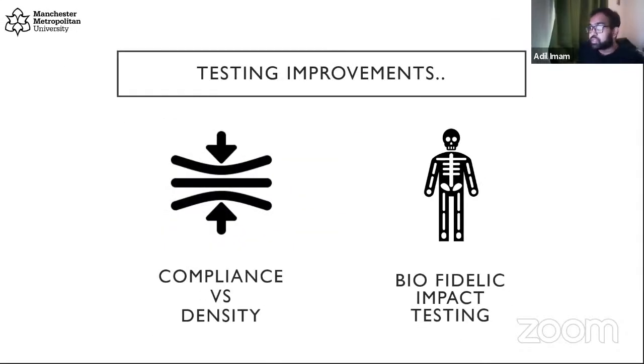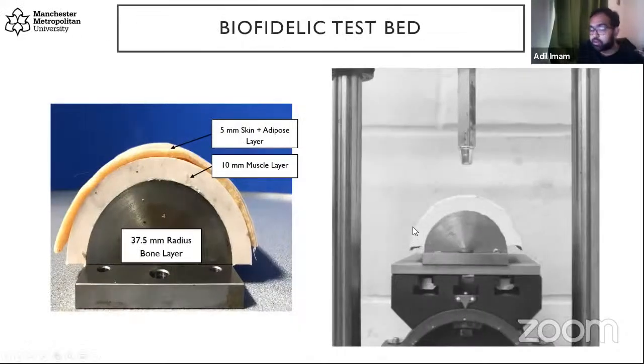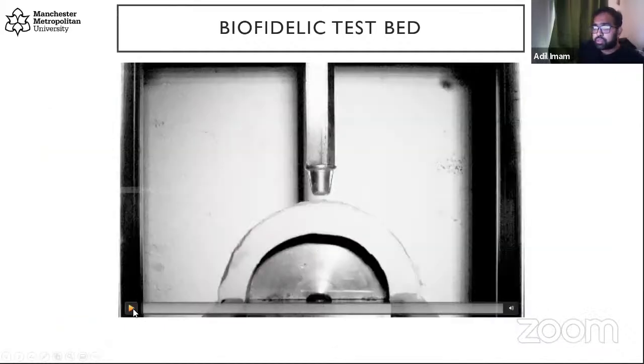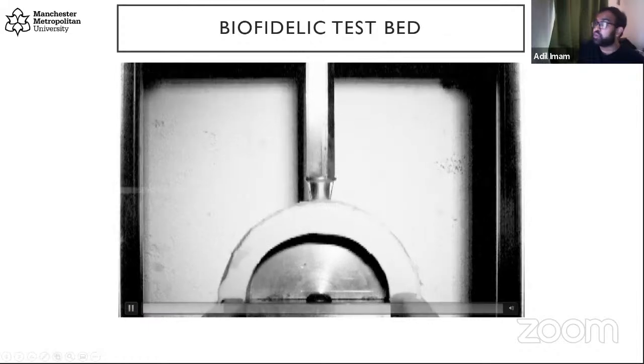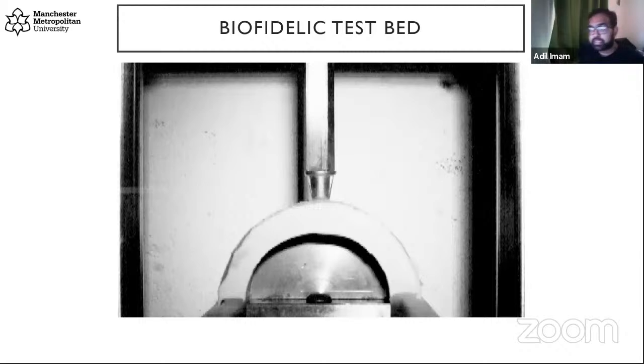One of the other things we did was develop a biofidelic impact test. Now, the impact test that is there, steel on steel, not very realistic. This project is working in combination with a researcher at the University of Sheffield. Now, Angus developed a test bed which is mimicking the shoulder area, a rigid core with a muscle layer and a skin layer on top. And we carried out some stud impact testing to mimic what would actually happen if a human skin comes in contact with the stud, which is usually worn in the game of rugby. So we carried out some impact testing, and I'm just showing the video of a perpendicular impact, but we did impacts at different angles as well.